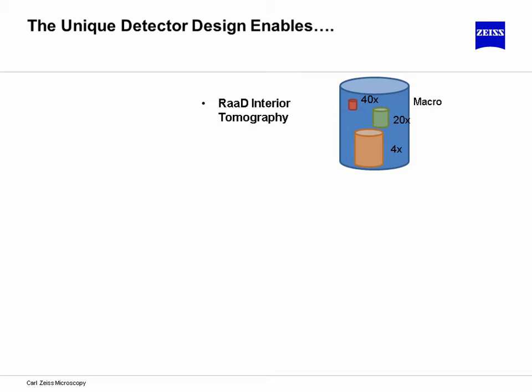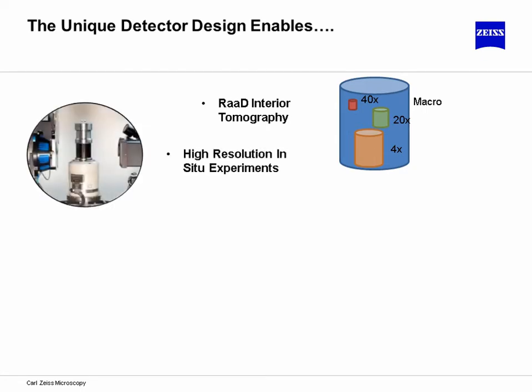Now, to summarize some of the key enabling features and applications that are now enabled with such an architecture for an X-ray microscope, the ability to perform interior tomography, which relies on resolution at a distance, or RAD, so virtually zooming in at high resolution to the interior of samples, but also being able to do fast scout scans that give you an impression of the entire sample, and coupling those, and even automating to some degree that procedure of essentially clicking to a region and performing a high resolution at any point in the sample that the user chooses.